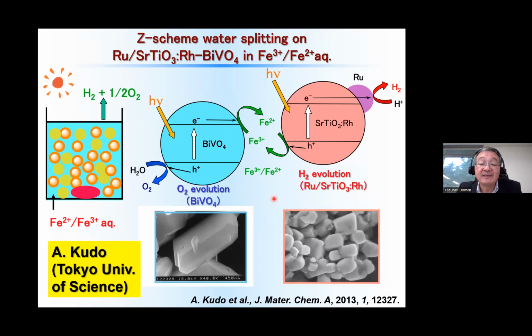And they used bismuth vanadate for the O2 evolution photocatalyst, and rhodium-doped strontium titanate modified by ruthenium for the hydrogen evolution photocatalyst. These two photocatalysts are connected by Fe2+/Fe3+, a so-called redox shuttle. They put all three components into a suspension system like this one, at low pH, I mean an acidic solution, to maintain the Fe2+/Fe3+ without precipitation.